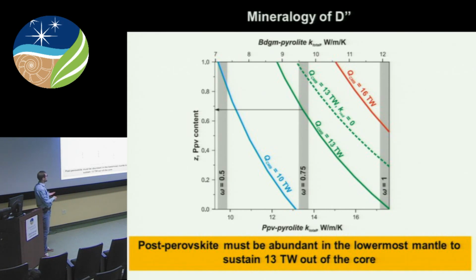So what are we changing again? Okay, 10 terawatts. Yeah, right. So basically this means that you can only have a 13 terawatt heat flow for a downward correction that is smaller than 25%. We don't know what this downward correction is, but if it is greater than 25%, you must have some amount of postperovskite at the least. Well, we're talking about 10 terawatts now. But for all heat flows that are greater than 10 terawatts, you must have at least some amount of postperovskite in order to sustain that heat flow.